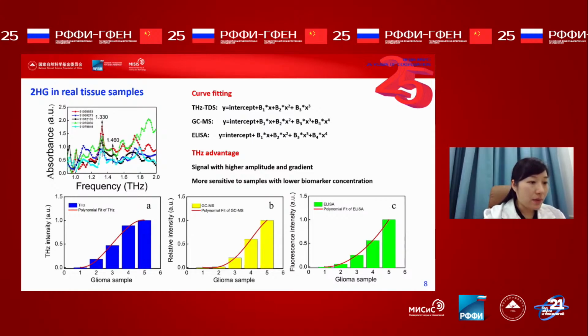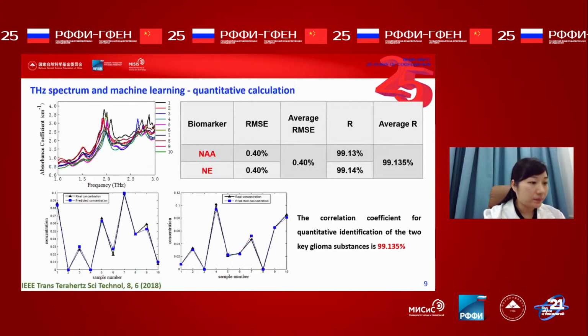Then we did experiments with rats and human tissues, and the results show that the terahertz method could obtain higher amplitude and gradient signal than GCMS and ELISA, and it was more sensitive to low concentrations of biomarkers. Next slide, please. The method of machine learning is used for quantitative calculation. The results showed that the correlation coefficients of quantitative identification of two key glioma substances were above 99%. Next slide, please.